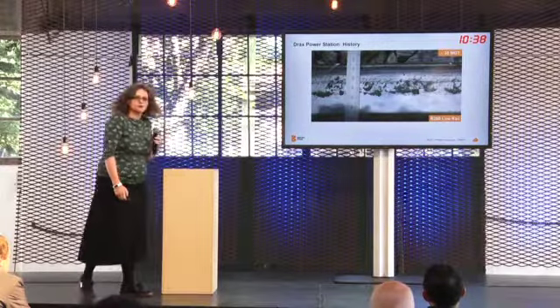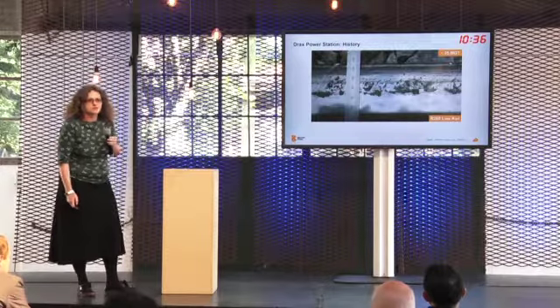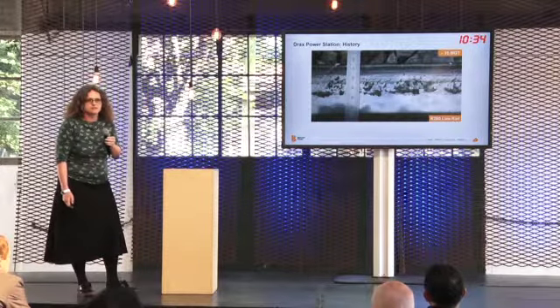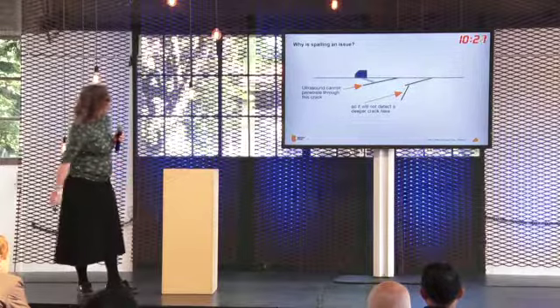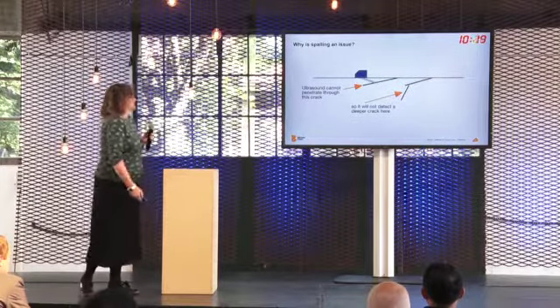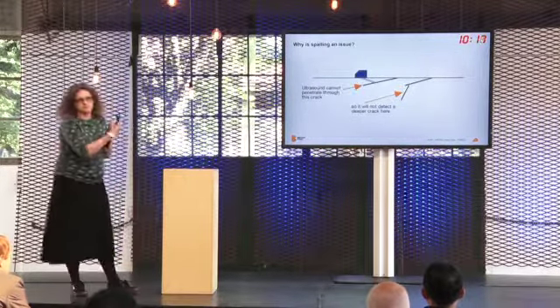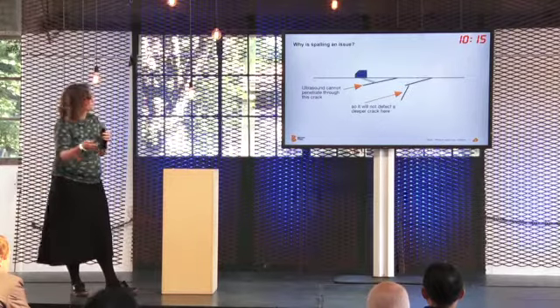So this is an example of the spalling that we saw on the R260, with large chunks coming out. The issue with that is ultrasonic testing. With these large chunks coming out, what you can't see with an ultrasonic tester is what's growing underneath. So at that point, the rail has to be taken out of service because you can't guarantee, as an example there, the ultrasound can't penetrate through that crack, so it will not detect the deeper crack underneath.